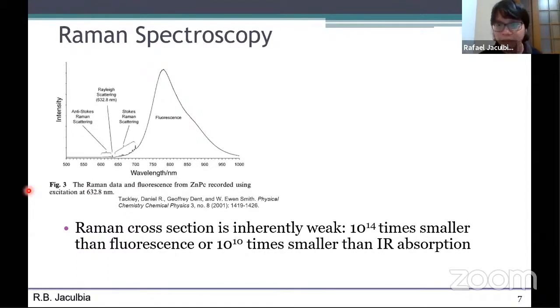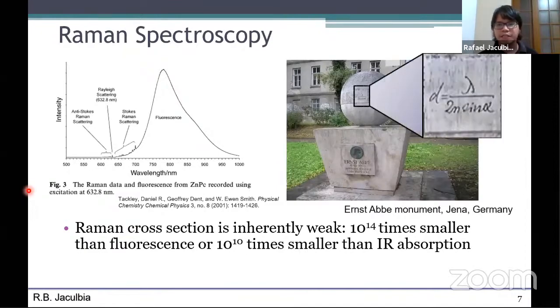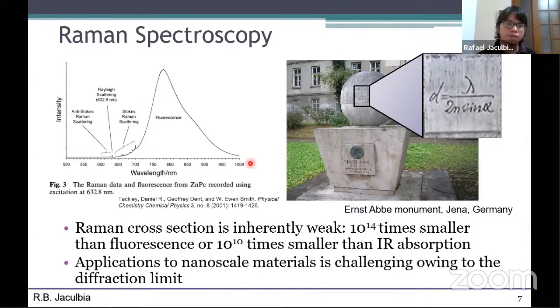So it was very difficult to measure Raman, but of course, recently the detection mechanisms, better cameras, and better filters allow us to detect Raman very easily. But in general, it's very weak. Moreover, Raman being an optical technique, it's limited by the so-called diffraction limit, wherein the minimum distance you can detect between two points in space is about half the wavelength. This means that if you use, say, visible light, the maximum spatial resolution you can get is in the hundreds of nanometers. Nanoscale materials in the 1 nanometer range are difficult to study with conventional Raman spectroscopy.